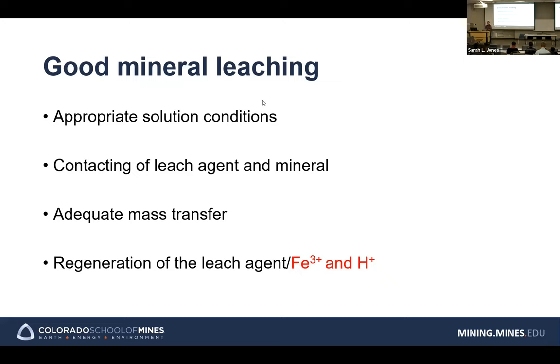So in a simple chemical reaction system, if you use a sulfuric acid to extract the copper, acid will be consumed. Acid will be consumed by copper extraction and also reacted with the gangue mineral. So how do we maintain the acid concentration? We have to keep supplying that chemical. But one of the advantages of the bioleaching, biooxidation system is that all those key reagents can be regenerated, such as Fe3 plus and H plus. So you reuse the iron oxidizing microorganism and also the sulfur oxidizing microorganism. So we can regenerate iron and acid.